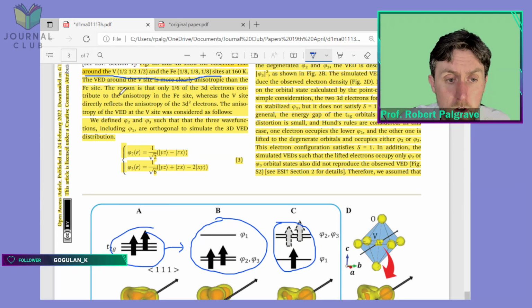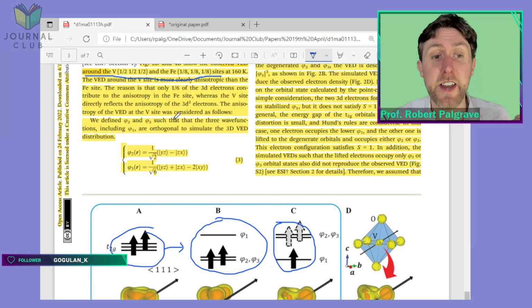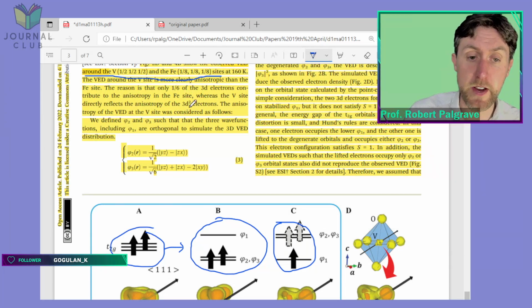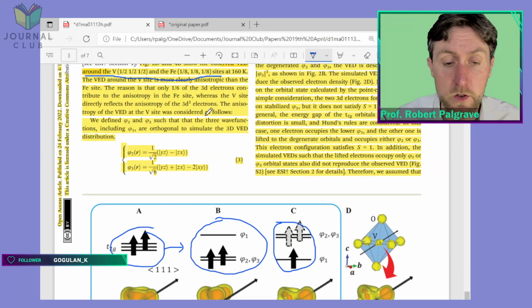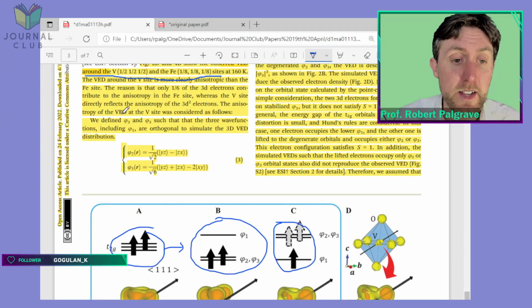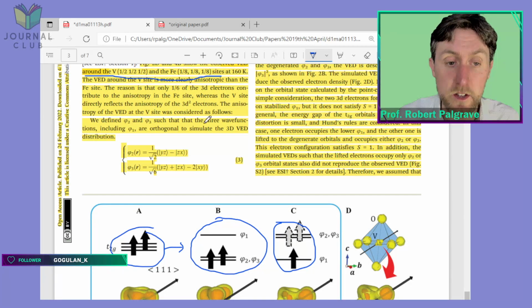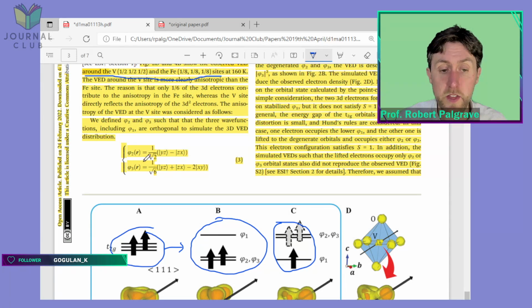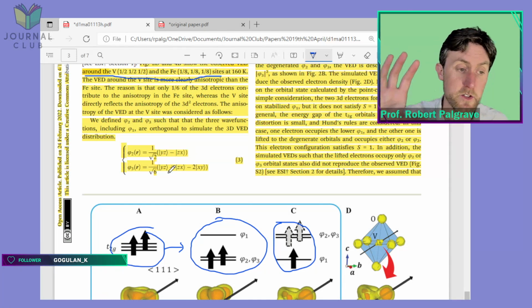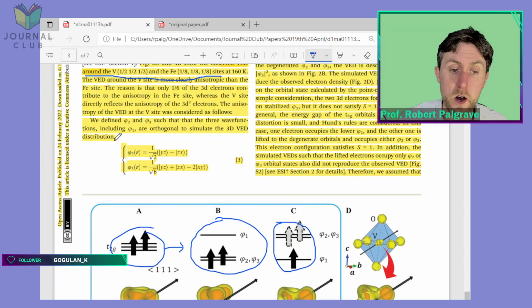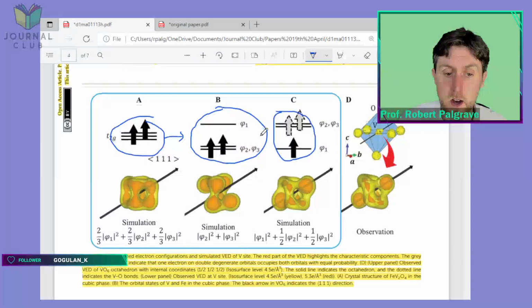Only 1/6 of the 3d electrons contribute to the anisotropy in the Fe site, whereas the vanadium site directly reflects the anisotropy of the 3d2 electrons. Both of the electrons contribute. The anisotropy of the valence electron density at the vanadium site was considered as follows. Again, thinking about their Jahn-Teller distorted octahedron, they have these 3 wave functions. Psi1 they defined earlier, and psi2 and psi3 are here.